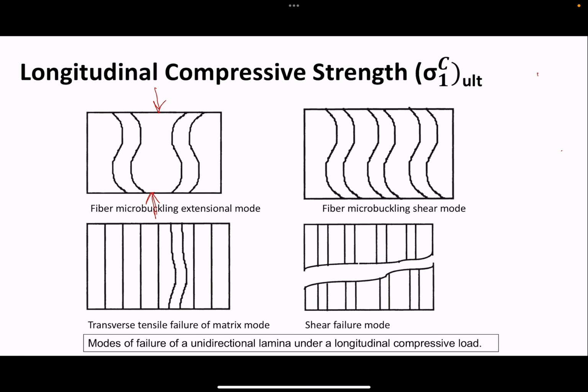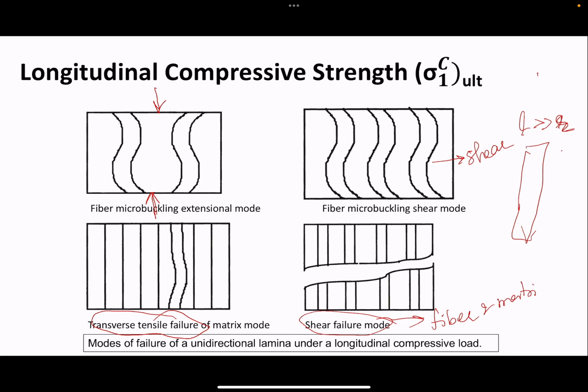So one is buckling. I hope you remember buckling. If you have long columns, where the length is very, very great compared to the cross section dimension, for example, then they might fail under compression or buckling. So here you can see that the fiber might buckle at the micro level, or it says transverse tensile failure here, which just means compression failure, or you might have buckling but also shearing that causes buckling. And then there's this shear failure mode where both fiber and matrix fail by shear. So these are 4 possible modes of failure.